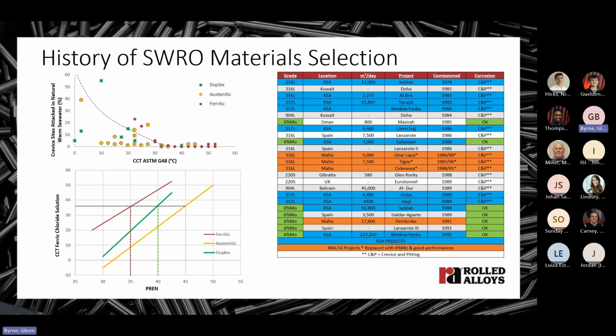By the 1990s, trial and error had largely established that 6% molybdenum superaustenitic stainless steels were the best solution for warm seawater service. But it wasn't until 1993 that the science caught up, and we had a simple lab test that correlated with corrosion resistance in seawater and focused our attention on the starting point for what we needed from a stainless steel for good seawater service. And that's a minimum PREN level.